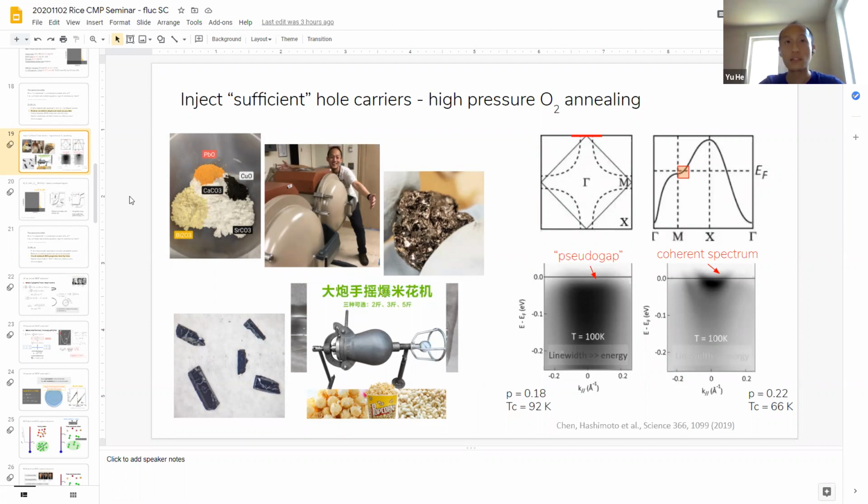On the other hand, when we do photoemission, we can do ozone surface treatment. In this case, it's no longer a bulk doping, but we can selectively just heavily oxidize the surface. Some preliminary data shown by the Brookhaven group suggest they can reach, I think, 29 or 30% doping, where superconductivity is killed. The problem with those types of surface treatment is that you can't really have an intrinsic measurement of TC. So it all comes from a guesstimation of the measured gap and Fermi surface volume.